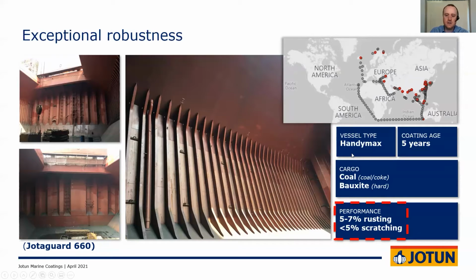So moving up the scale, the result you can see here is for a Handymax bulk carrier, which has predominantly been trading with coal and bauxite, to which the coatings have stood up fantastically well after 5 years in service this time. So the result being less than 7% rusting and less than 5% scratching. Certainly not needing any major refurbishment at this stage, probably for another few years at least.